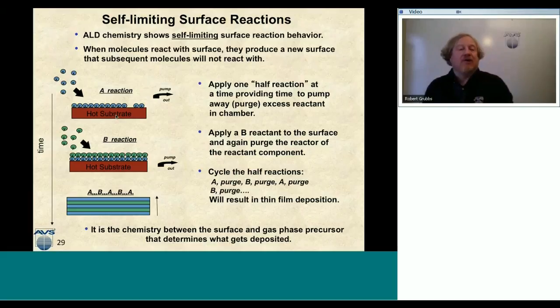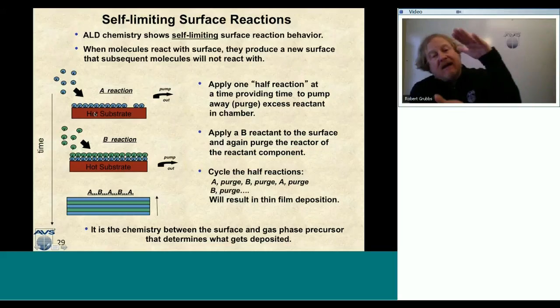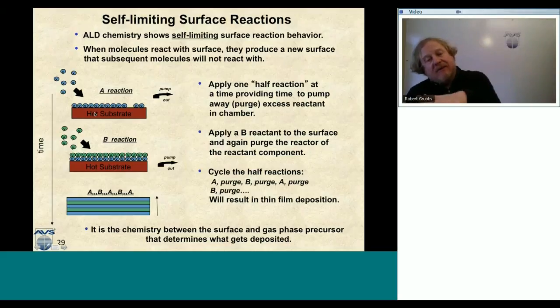So here in my cartoon, we have a hot substrate. We come down with A. They react on the surface, but we don't build a multi-layer of material on this surface. They just react on the surface and then they stop. And that is the self-limiting behavior of the surface reaction. So once the surface is saturated, we can proceed with the pump out plan and know that the surface has as much of this A reaction as possible.